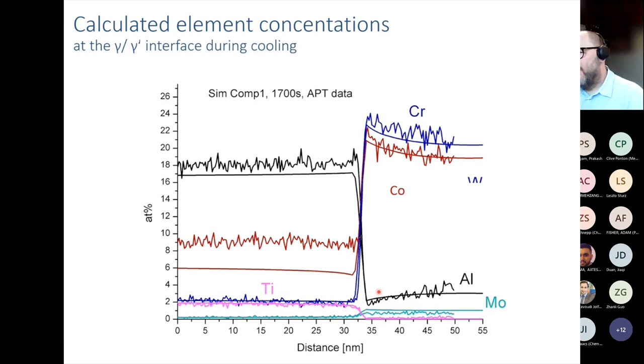We found that during the cooling of the sample, which was meant to be a fast cooling, the interface had moved just a few nanometers, really. It's not very much, but it had moved, and that little movement was sufficient to build up a pileup ahead of the moving interface, which would perfectly explain the variation in concentrations that we saw in the atom probe data.